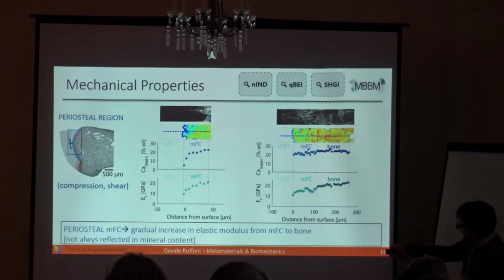If we do this up here where there is no tendon, this is when we go from unmineralized tissue to bone, and we see a gradual transition in calcium mineral content, and we see that the Young modulus also follows quite nicely this gradual transition. So we can see a graded material.